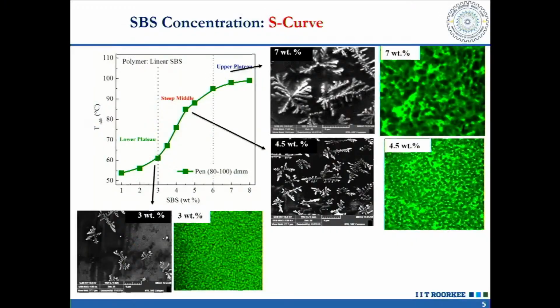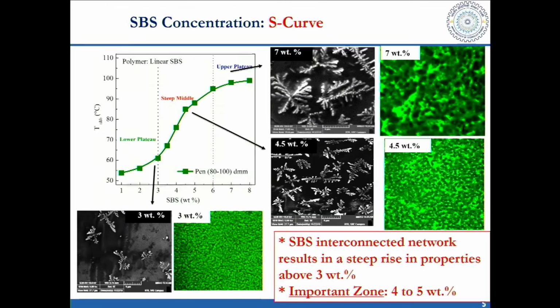The fluorescence microscopy shows the lighter phase, which is the green phase, due to the polymer, and the darker phase, which is due to the bitumen. So when you increase the SBS concentration, the density of the lighter phase increases, which indicates strong network formation in the PMB. The conclusion of this slide is that the SBS interconnected network results in a steep rise in the property above 3%, and the most critical zone is 4 to 5 wt.% in the bitumen.